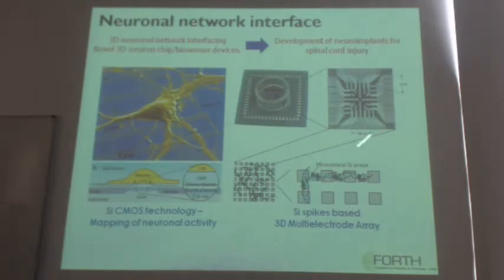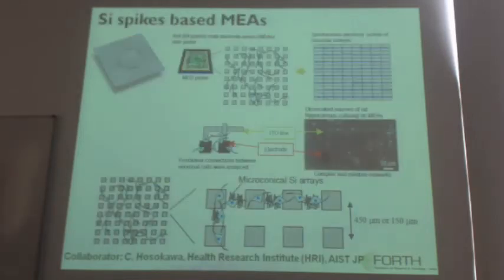And the second step toward this direction is to realize a 3D multi-electrode array based on silicon spikes. There are commercially available multi-electrode arrays based on silicon, so we can modify these arrays. Here is the concept. Here is the MedPro. This is the commercially available multi-electrode array probe that we use in order to study this difference.